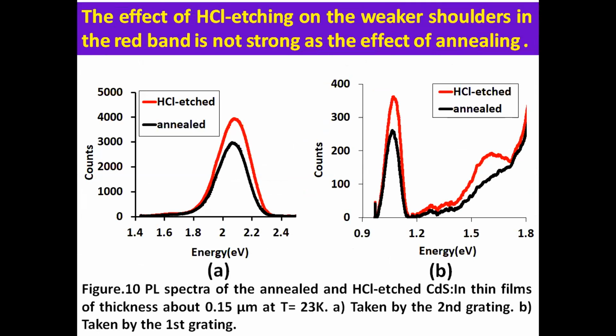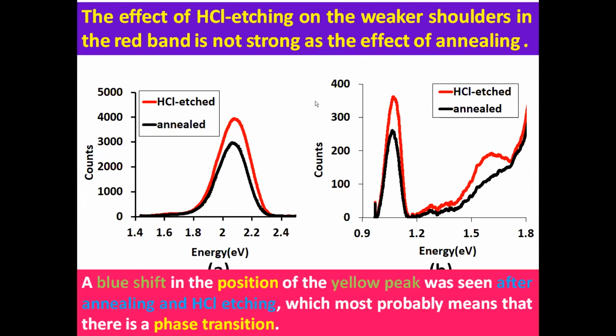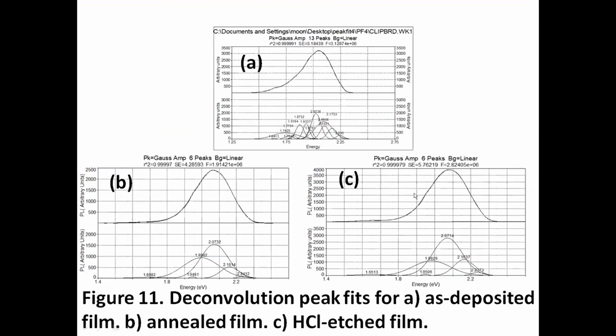Now here is a comparison between the as deposited film, annealed film, and HCl etched film. We see the number of peaks is decreased after annealing and etching, and a blue shift of the peaks has occurred in both cases.